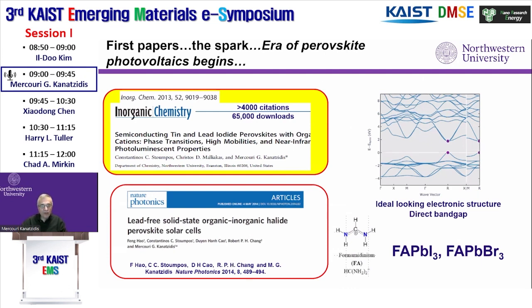Now, because of the work we did in the years prior to our publication, we had a lot of knowledge and a lot of experimental data about these perovskites, almost 20 compounds with different cations like methylammonium, formamidinium, cesium, and different halides. We published this paper in Inorganic Chemistry that contained basically all the correct, reproducible synthesis, crystallographic data, coordinates, properties, property trends, and explanations of the property trends. And this paper came out at just the right time, when everybody was trying to find information and understanding of these materials.